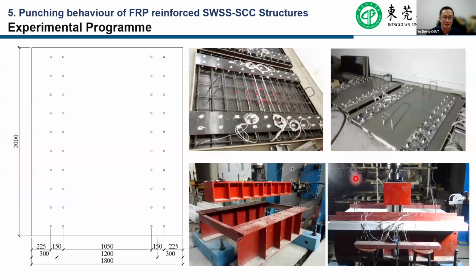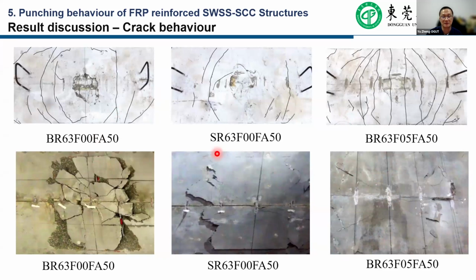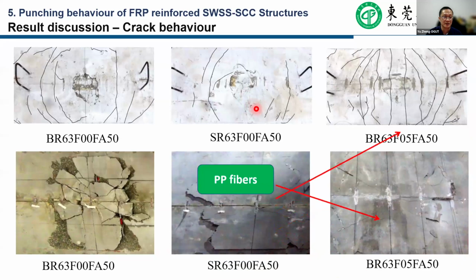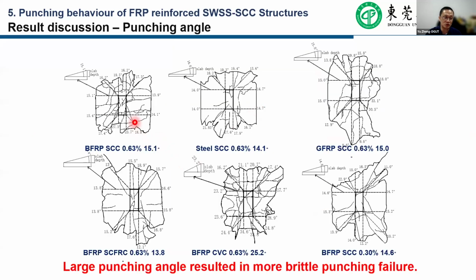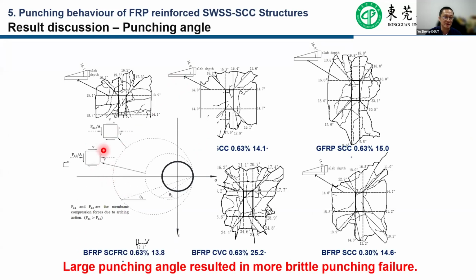This shows the test specimen preparation in my study. In the test results, we find that punching behavior is dominant in all the specimens. But if we use PP fibers inside the self-compacting concrete, the failure is not so brittle compared to the model without the PP fibers. Furthermore, we investigate the punching angle, because we found that smaller punching angles mean larger contact areas in the concrete.